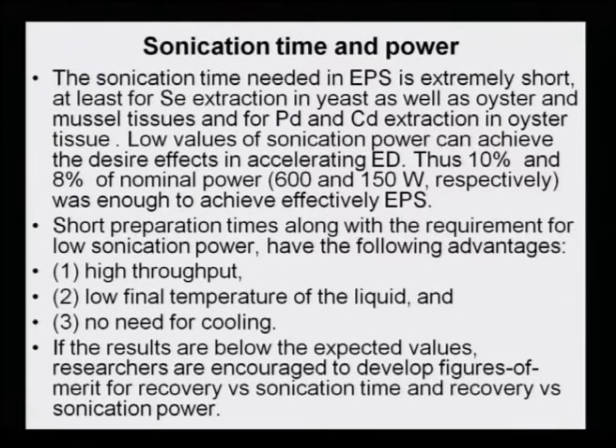Sonication time and power. The sonication time is very important and needs to be understood very carefully in EPS, and it is extremely short, at least for selenium extraction in yeast as well as oyster and mussel tissues, and for palladium and cadmium extraction in oyster tissue. Low values of sonication power can achieve the desired effects in accelerating enzymatic digestion. Thus, 10% and 8% of nominal power, which is 600 or 150 watts respectively, was enough to achieve effective EPS. Short preparation times along with the requirement for low sonication power have the following advantages.